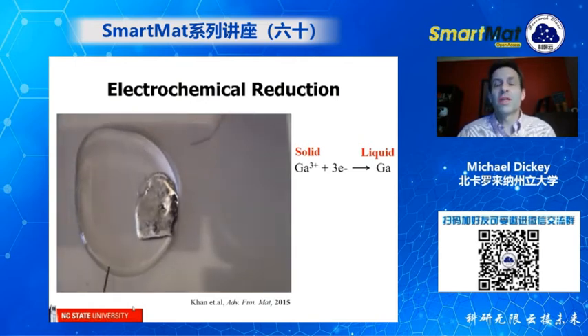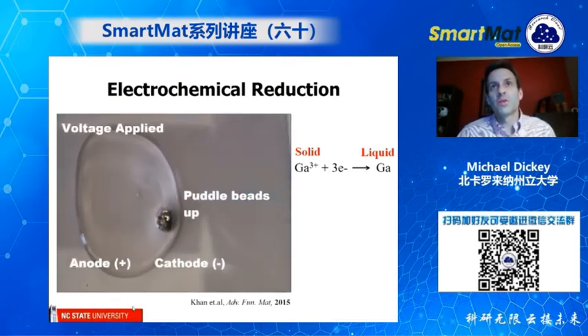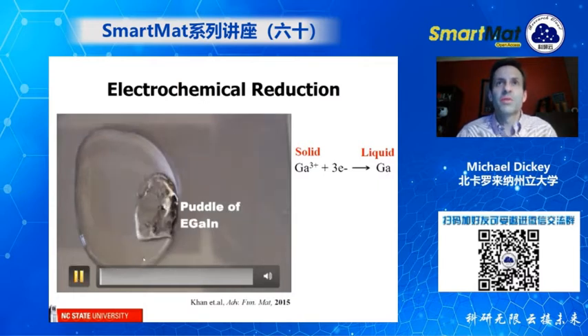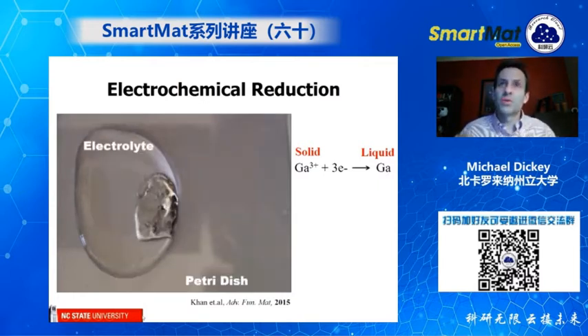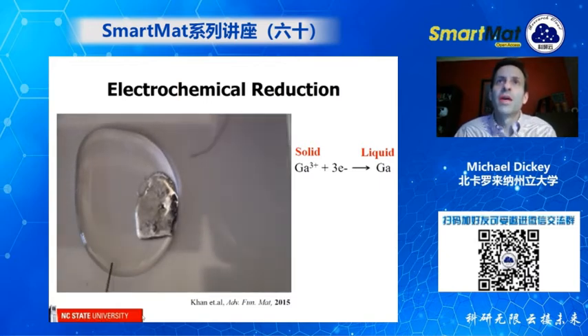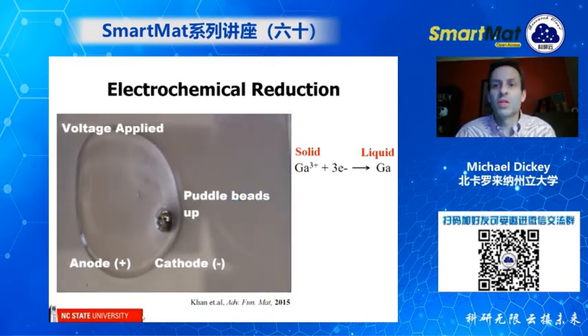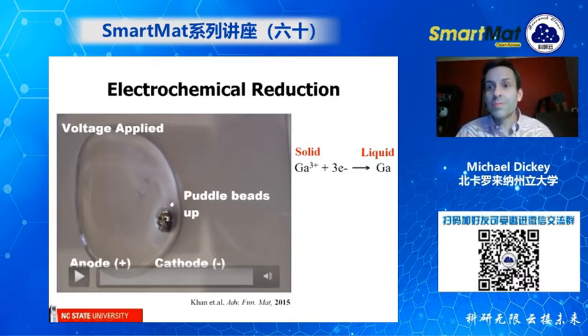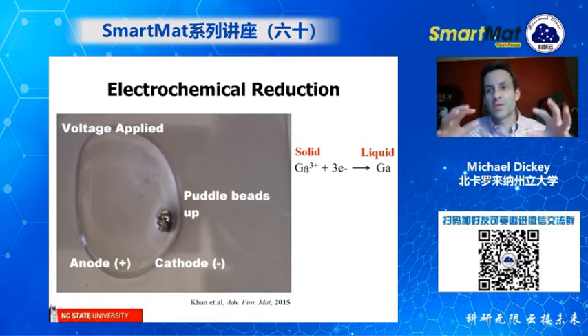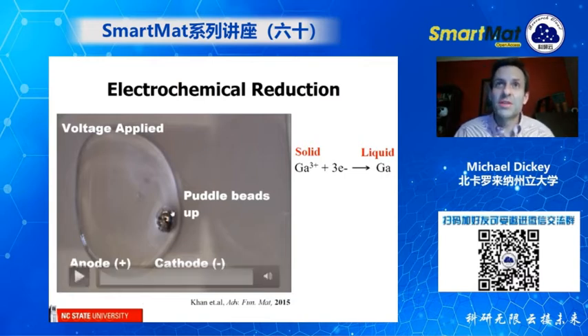And we can remove it using electrochemistry. So here we take 2 electrodes and we apply a voltage. I'm going to play this one more time. This is the liquid metal. This is salt water. And we just take 2 electrodes and we apply a reductive potential. Now that reductive potential removes the oxide layer and causes the metal to bead up, and you'll see bubbles form. Those bubbles are hydrogen bubbles. So this is the very oversimplified reaction, but basically oxidized gallium, which is on the surface, you can reduce it and it forms liquid. So what's interesting is you see here, it beads up, it tries to minimize its area.